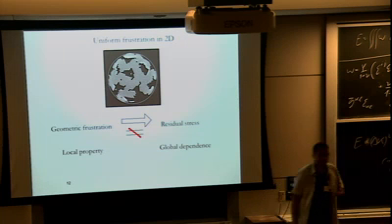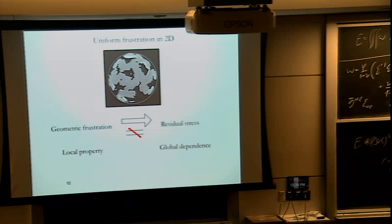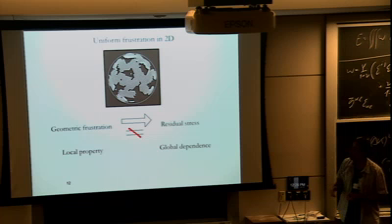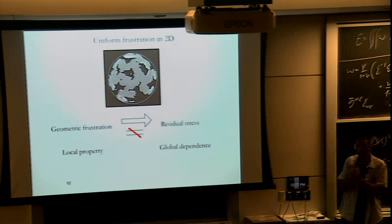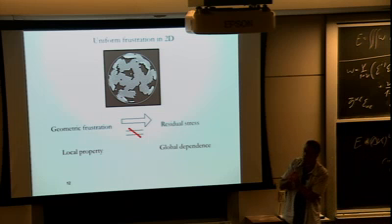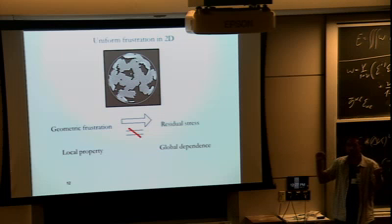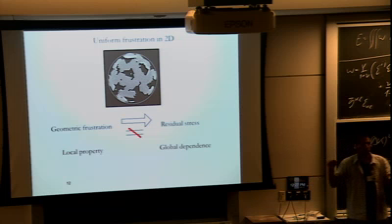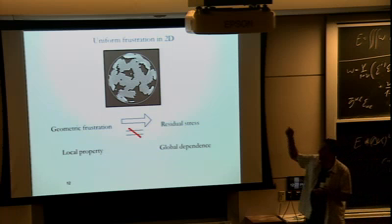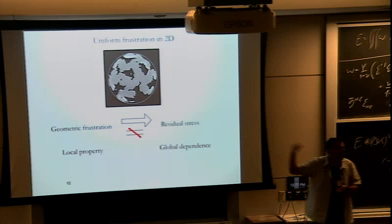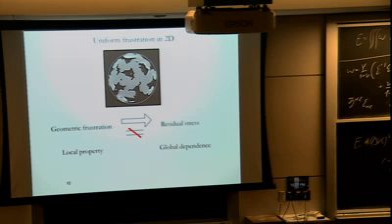One may ask legitimately, why don't we see this everywhere? Why, or to some extent, what made this system very, very special? What made this system very special is the fact that the interactions between the colloidal particles were so short-ranged that defects were completely precluded from the system. Particles rather remain in the melt than make a 5 or a 7 defect in this crystal. And that tells us also why we don't see this commonly.